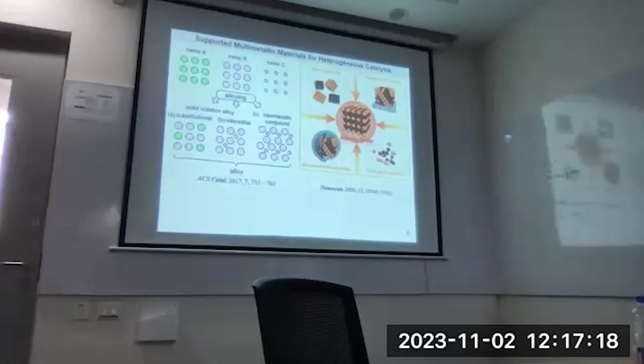This is what my PhD work was about, so I'll be focusing entirely on this. Colloidal co-reduction can only be used for a limited number of processes, like mild liquid phase reactions where the temperature is relatively low, below 150 degrees Celsius. As you increase the temperature, these things will aggregate and form bigger particles and you lose the surface.